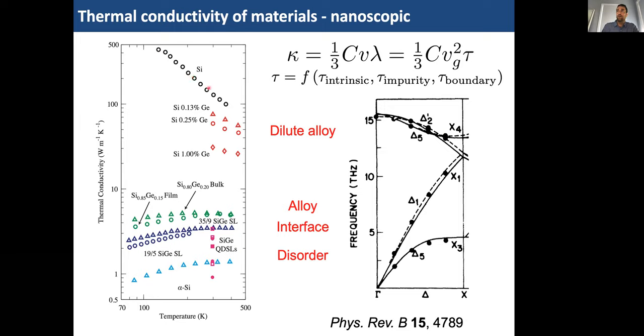The thermal conductivity of bulk silicon is an intrinsic value to silicon. It's intrinsic to something called the silicon dispersion curve. So this is the phonon dispersion curve of silicon. What the phonon dispersion curve of silicon tells you are the allowable energies and velocities of phonons in silicon. You'll notice there's a set bandwidth of phonons in silicon, and the derivative of this curve is the speed of the phonons, where the energy of the phonons is given by the frequency.